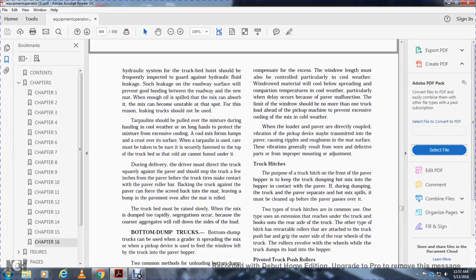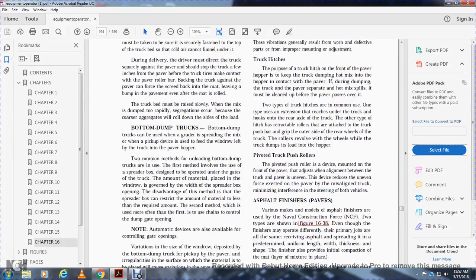The pickup machine prevents excessive cooling and mixing in cold weather. When the loader and paver are directly coupled, vibration from the pickup device may be transmitted into the paver, causing ripples and roughness in the mat surface. The vibration generally results from worn defective parts or improper mounting or adjustment.